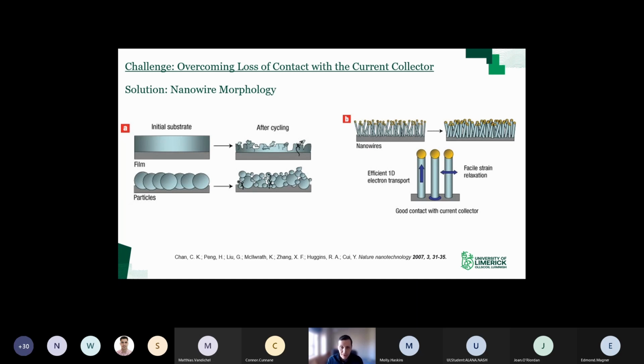Nanowires are a very good anode material because you can grow them directly from the substrate, directly from the current collector, which means you don't need binders or conductive additives, which are inactive materials that would be used for graphite electrodes, for example. They're inactive, so they don't add to the capacity. They reduce the overall specific capacity of your anode. You don't need those for nanowire-type anodes. So, like I said, Professor Yi Cui at Stanford pioneered this technique, using nanowires grown directly from current collectors as the anode material.